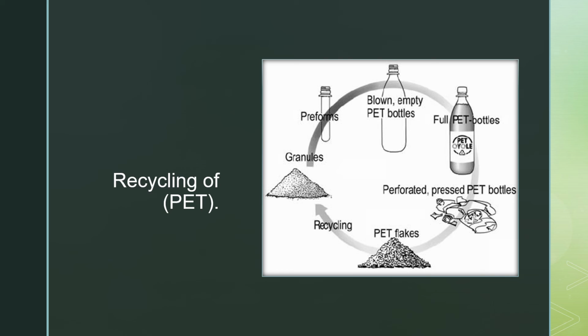Post-consumer PET bottles are collected and processed through a series of special washing processes or by a chemical treatment to break down the PET into its raw material or intermediates, which are further used to produce recycled PET flakes. The growth of bottle recycling has been facilitated by the development of processing technologies that increase products' purities and reduce operational costs. The most adopted methods for PET recycling are chemical recycling by hydrolysis and mechanical recycling, with chemical recycling involving the production of terephthalic acid and ethylene glycol to utilize them for making other synthetic chemicals.